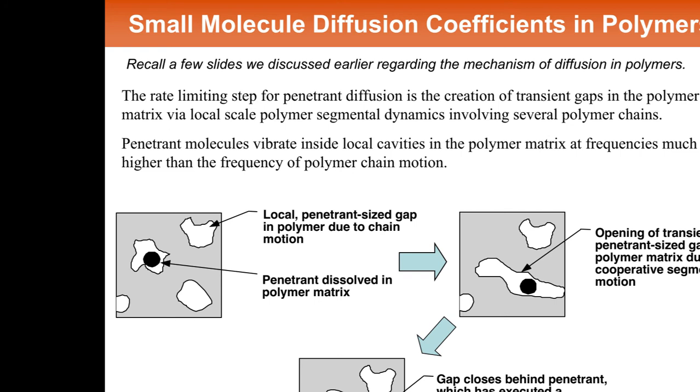And I showed you this one earlier. It's molecular dynamics studies in poly-2,6-dimethylphenylene oxide. Here, the polymer has been built in a simulation box at its experimental density. It has been endowed with thermal motion, and then Newton's laws of motion are solved for each of the atoms in the backbone. Then oxygen and nitrogen molecules are unleashed inside this simulated polymer, and their motion through the polymer is tracked. And you can see that over time scales for oxygen of like 1,000 picoseconds, you can watch it move away from its origin via random diffusion.